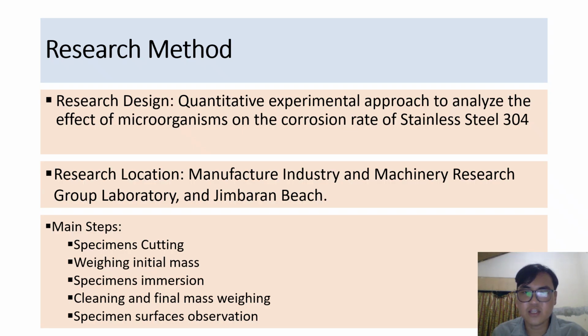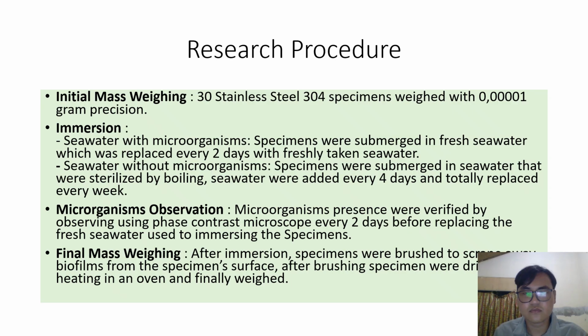Moving to the methodology, this study utilized a quantitative experimental approach. The research was conducted at the Manufacturing Industry and Machinery Research Group Laboratory and used seawater collected from the Jimbaran Beach. The process involves specimen preparation, initial weighing, immersion, and final analysis. Our procedure begins by weighing 30 specimens of stainless steel 304 with a high precision scale.